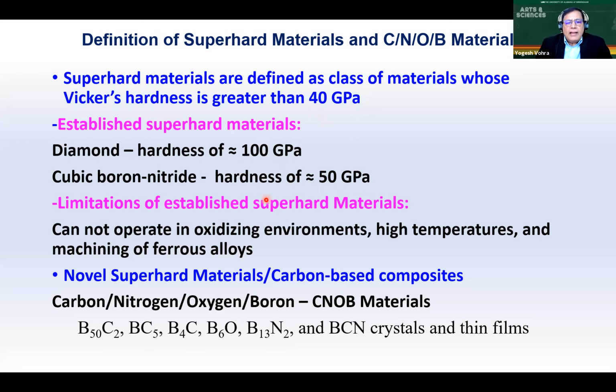So why are we looking at new materials? That's because there are certain limitations at high temperatures. For example, diamond tends to oxidize in air beginning at as low as 600 degrees Celsius. So it's not meant for high temperature application in oxidizing atmospheres. Cubic boron nitride is a bit better, but is also limited to about 1,000. But there are applications where you need higher temperatures and also high hardness.